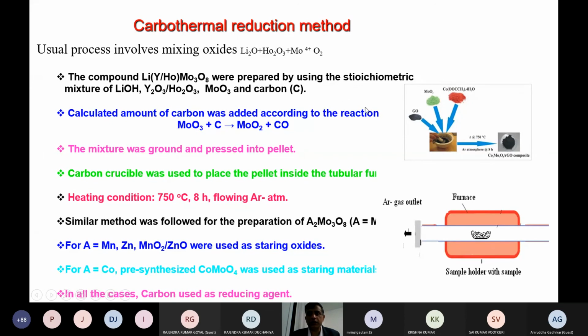We use a carbothermal reduction approach, in the sense that you take MoO3, react it with a calculated amount of carbon, and finally we can get the respective mixed metal cluster compound. The beauty of this method is that you don't need any sealed tube reactions. With a simple tube furnace under argon atmosphere, we can prepare the material. Remember, for any carbothermal reduction method, make sure the minimum temperature is 750. Don't try to prepare the sample at low temperature, it will not react. The carbon has to react. Based on our experience, the minimum is 750 degrees, or in some cases we can go to 700 degrees. So remember the logic behind this.